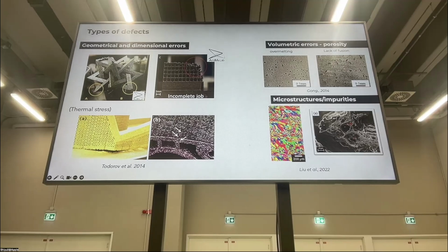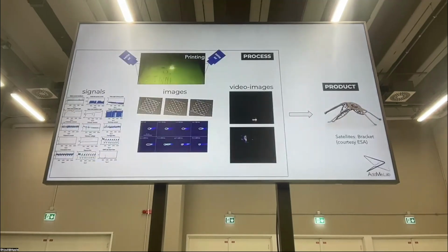And I will also spend some time on the new direction that is going in the direction of microstructure tuning. Microstructure means that all the colors that you see are grains inside the part. And depending on the size and the orientation of these grains, you can have quite different mechanical performances at the end. So tuning the microstructure, which is due to the way in which you are melting and cooling the part, is going to affect the mechanical performances at the end.